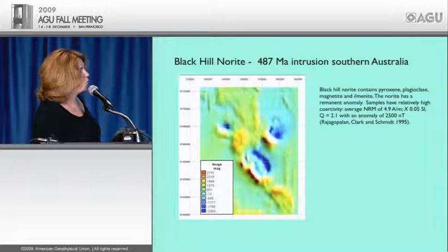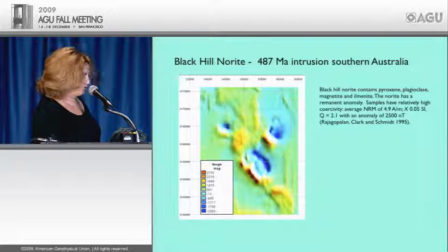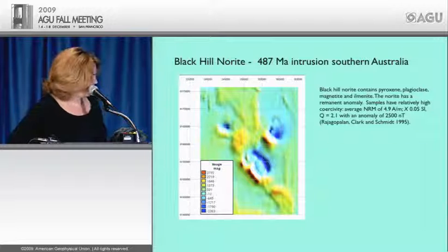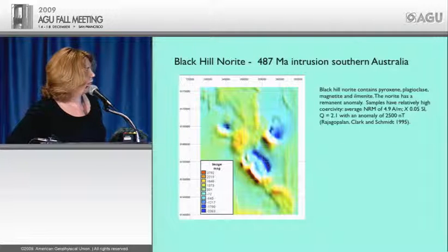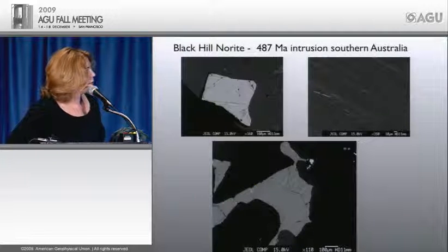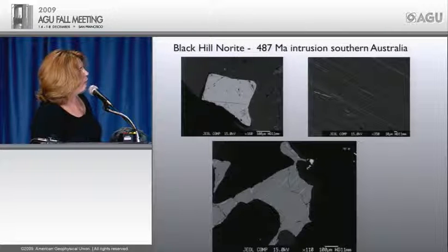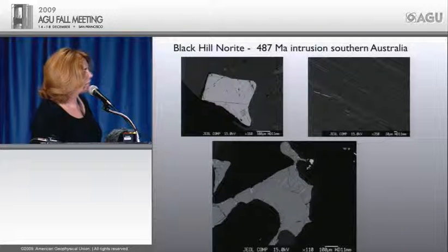Now, I briefly want to move to the Black Hill norite in Australia. And this also has a very beautiful negative anomaly associated with it. And here we have magnetite with some minor oxyexsolution of ilmenite. We have pyroxene with ilmenite exsolution and a little bit of magnetite in there. And we also have ilmenite.